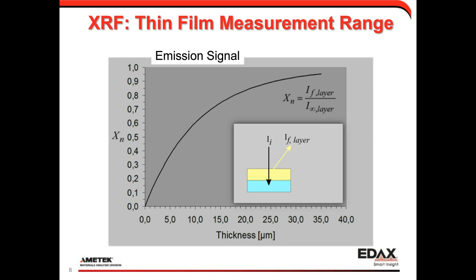So on the x-axis, you have thickness. And in this example, we're running out to something like 40 microns. And on the y-axis, we're looking at the X-ray signal. And we're dividing that X-ray signal by the intensity that we would get from a layer that is infinitely thick with respect to X-ray. So you don't get any more response out of it if your layer gets thicker. So basically we're normalizing to a value of 1 at that point. And what you see is that as the layer gets thicker and thicker, our signal ratio approaches a value of 1 because the layer basically becomes infinitely thick.